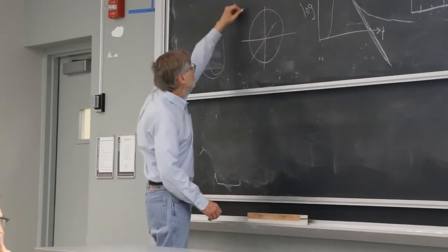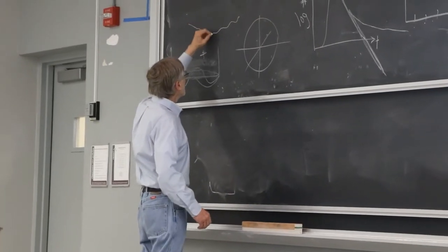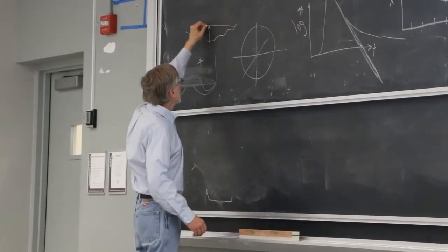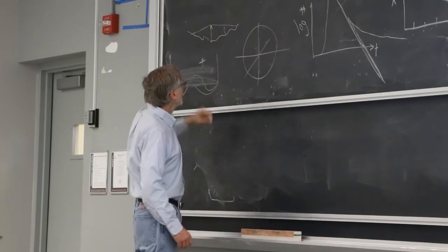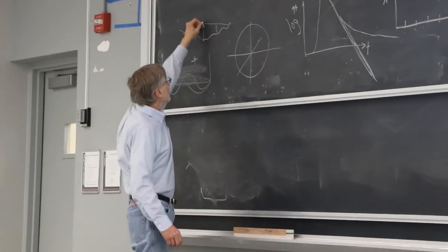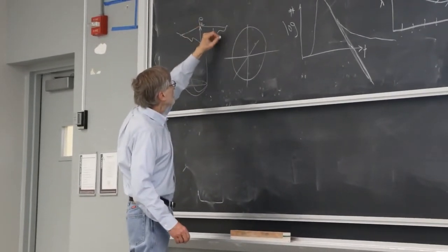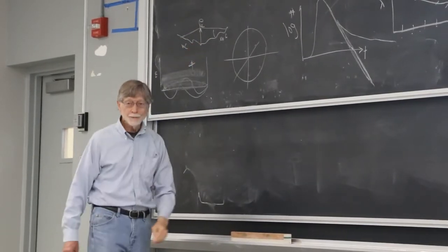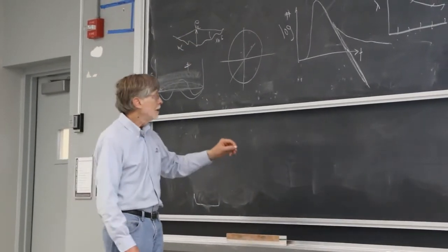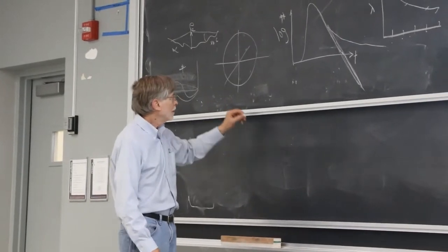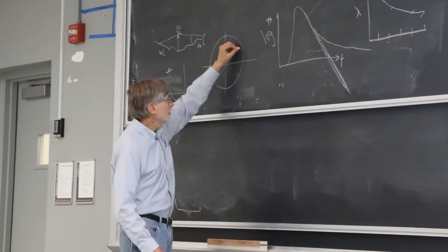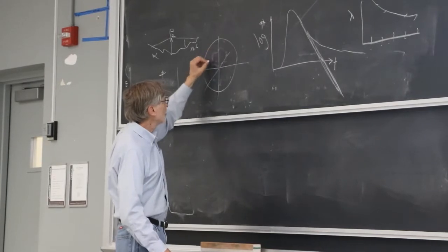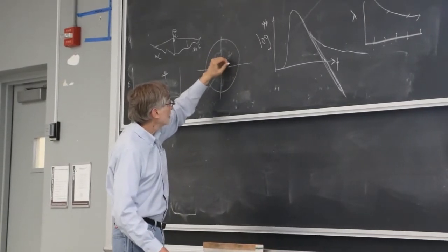So you've got two photons like that, and you've got some net momentum like this, and that gives you an angle between them, which tells you the electron momentum. This is mc, this is mc, and the angle between them tells you the electron momentum. And when you plot those in 2 dimensions, it gives you a sphere of uniform occupation, like that.